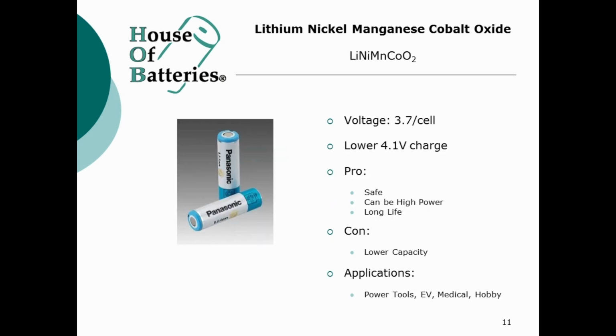After the development of lithium cobalt oxide and lithium manganese oxide cells in the 1990s, engineers turned next to blending different materials with the cobalt in the cathode to achieve different results. By reducing the amount of cobalt in the cathode, they are able to reduce the manufacturing cost because cobalt is an expensive material. And by using different amounts of nickel or manganese, nickel and aluminum or other materials, they can achieve different specific characteristics such as high rate discharge capability or high energy density or runtime.